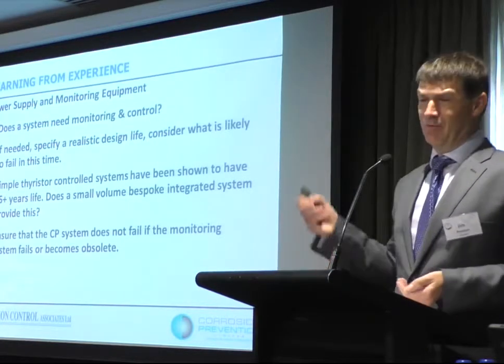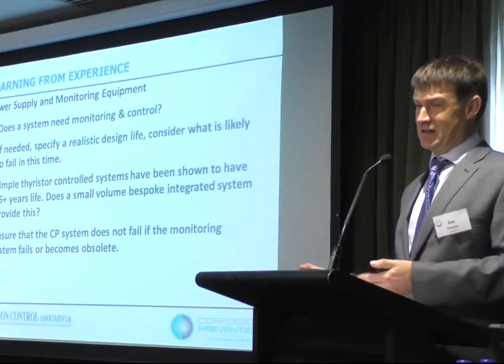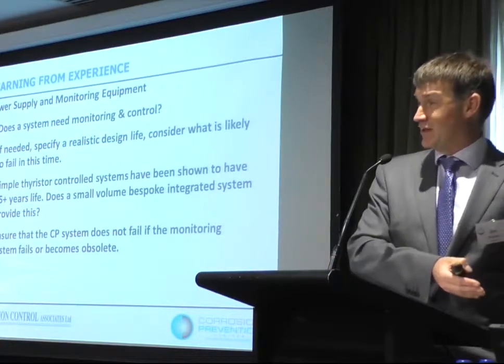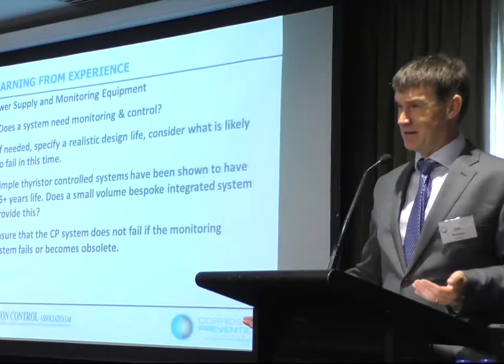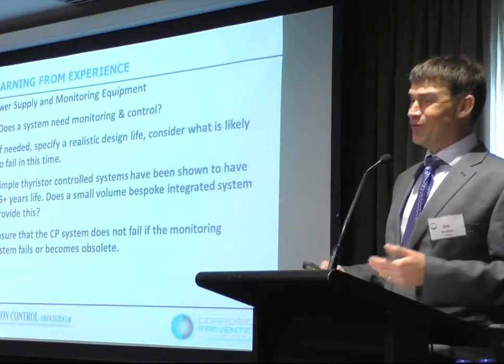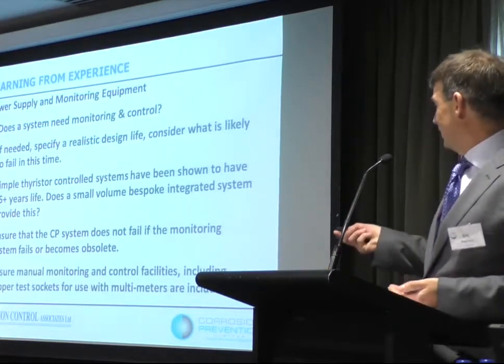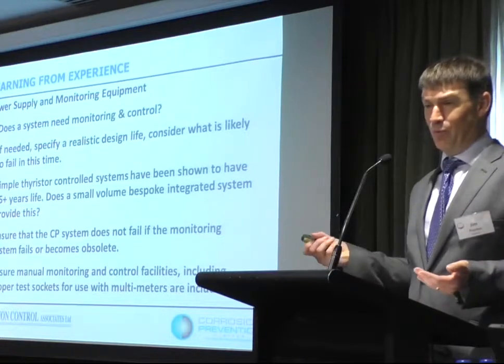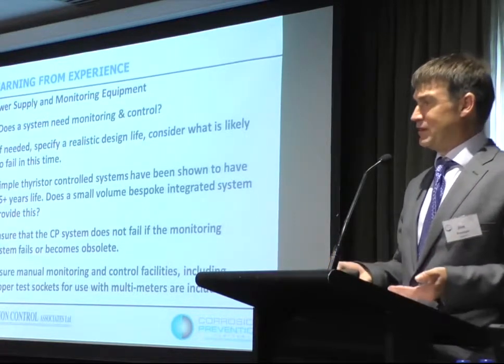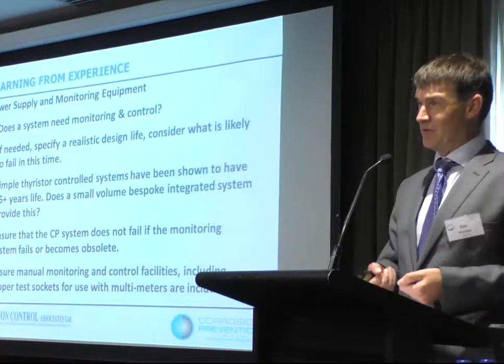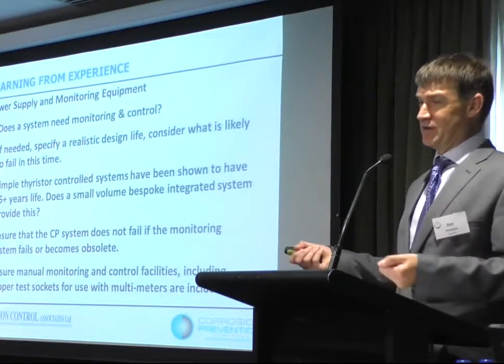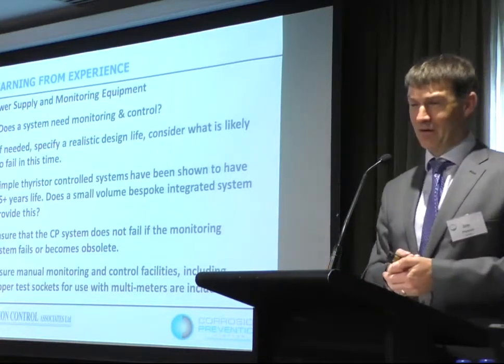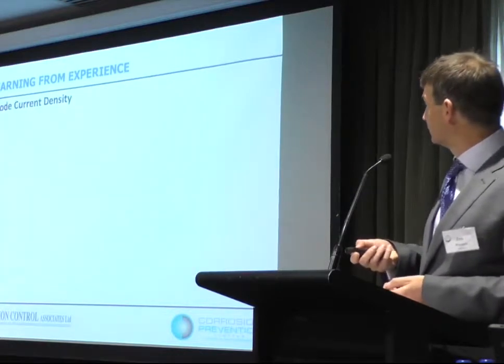And we need to make sure if the monitoring system fails, it doesn't actually take out the performance of the cathodic protection system. It should be there to monitor the system. It shouldn't be there to run the system. And we always specify now that systems must have manual facilities, so we can at least come along with a multimeter and see what's going on. We haven't got this issue where if the PC's not there, we can't actually see what's going on.